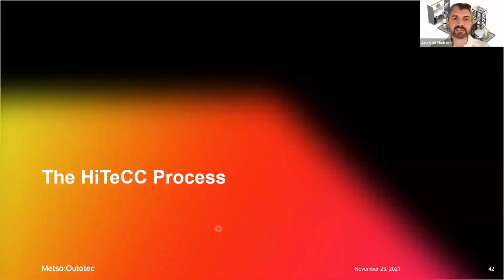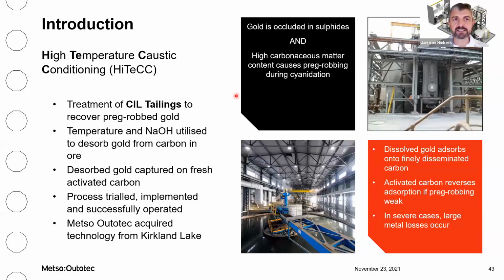Next process I'd quickly like to touch on is the HiTeCC process. Like I said, this is a chemical process. It's not a biological process, it's a chemical process for the treatment of CIL tailings to recover preg-robbed gold. And in this process, we basically utilize temperature and solution chemistry, through the addition of caustic, to dissolve gold from preg-robbed carbon in the ore. And this dissolved gold is then captured on fresh activated carbon.